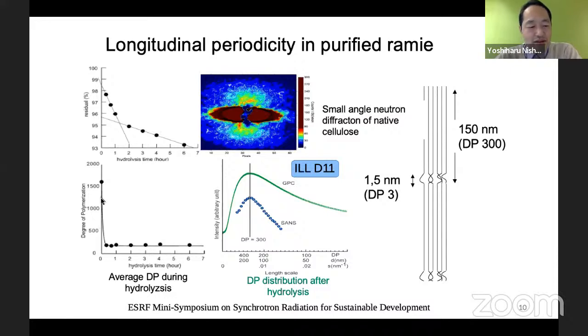And the reason why this rapid decrease in degree of polymerization happens, and also why it is stable after the first drop, was a kind of mystery. One thing we have done with neutron scattering is we just soak this fiber into heavy water and look at the change in the scattering pattern before and after this heavy water exchange, or deuterium exchange.